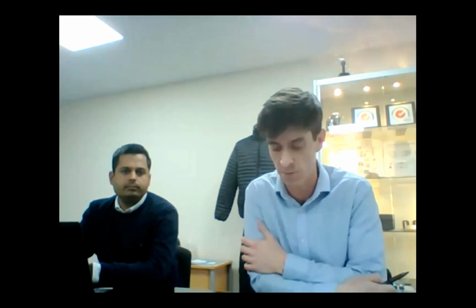So there's two aspects there. The first thing I'd like to mention is we can oxidize graphene through our process. So we can get up to 28% oxygen on the surface of the material, and that's with no oxygen tied up in impurities as well. So we can generate what we like to call plasma oxidized graphene oxide. But as you mentioned, it is insulative. So for this application, if we do want any specific oxygen groups, we would only put as much as needed, sometimes as little as 4%, to help interact with the matrix. And then that is less detrimental to the electrical conductivity of this material.